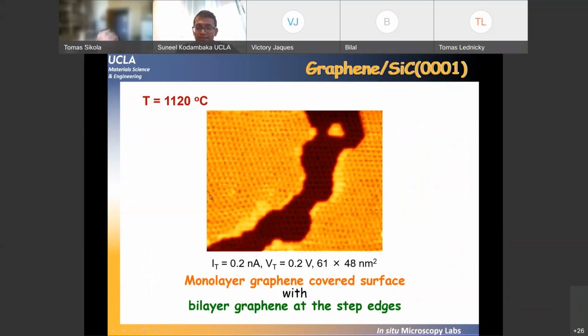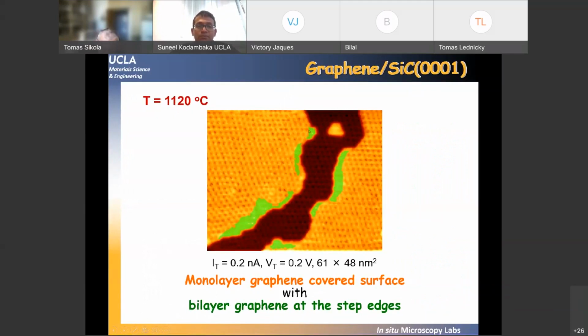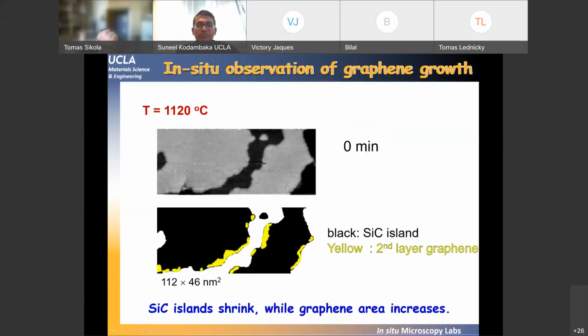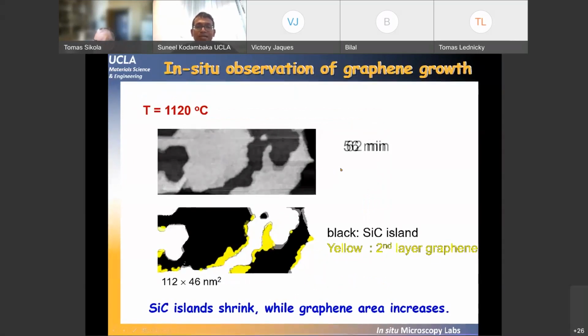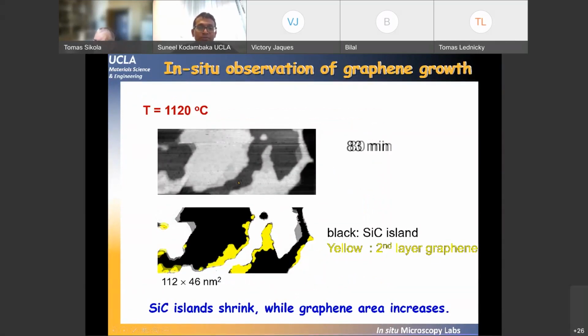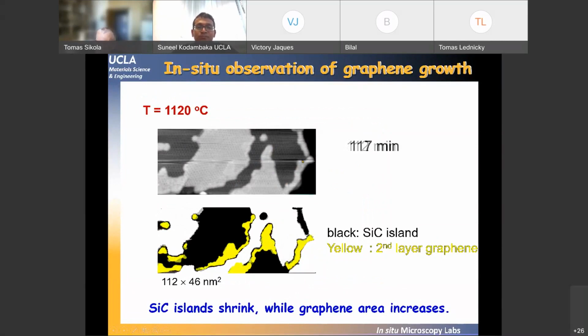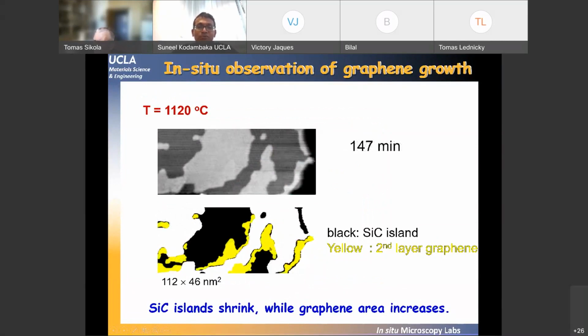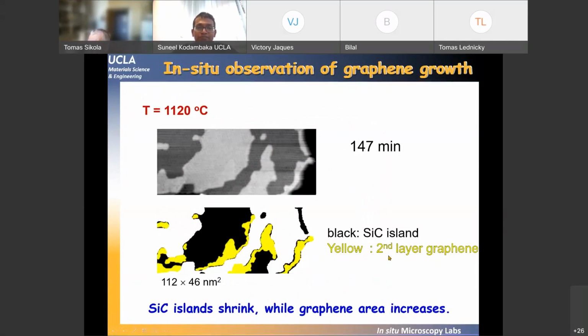And what you're looking at here, color-coded, is a monolayer graphene covered surface, and the regions that are colored green are the bilayer graphene. And we watch this surface as a function of annealing time. What you're going to be looking at are time-lapsed images obtained over 140 minutes. And you see the surface changes. And here the silicon is desorbing from the surface, leading to the formation of the bilayer graphene.